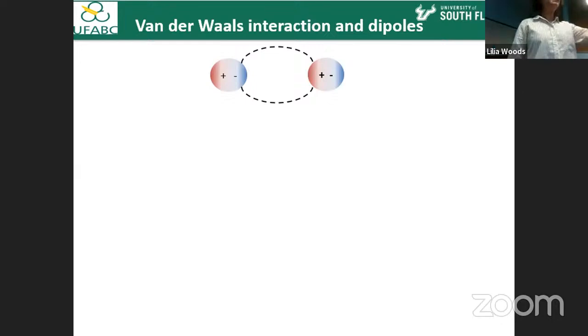So if I take one atom and place it in vacuum, vacuum of course is not empty, it is filled with electromagnetic fields. These electromagnetic fields constantly experience virtual flickering. They keep appearing and disappearing, flickering electromagnetic modes. Well, if the atom is sitting there, the atom is going to respond to these flickering fluctuations. And the way the atom responds is by creating an instantaneous displacement of the positive and the negative charge that make up atoms. That means creating virtual dipoles. So this is the response of the atom to the surrounding electromagnetic field.